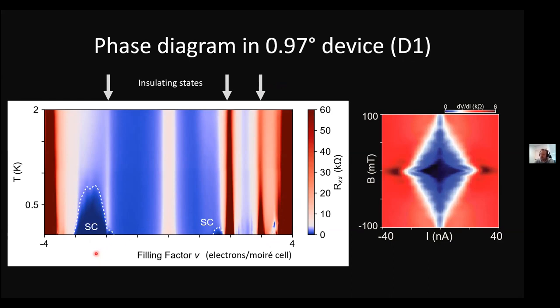And in all our experiments, in addition to measuring the temperature dependence, we always verify the superconductivity by acquiring this Fraunhofer-like pattern. This is just a sanity check that we are not in some fake superconducting regime, that this is a real superconductor.